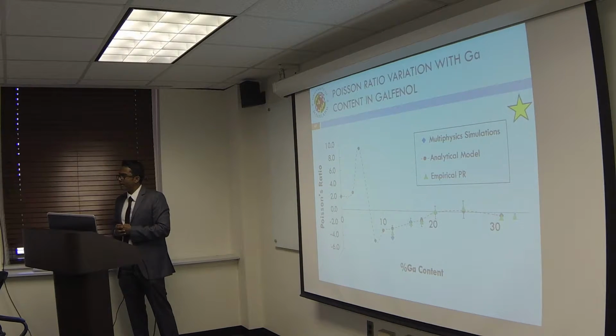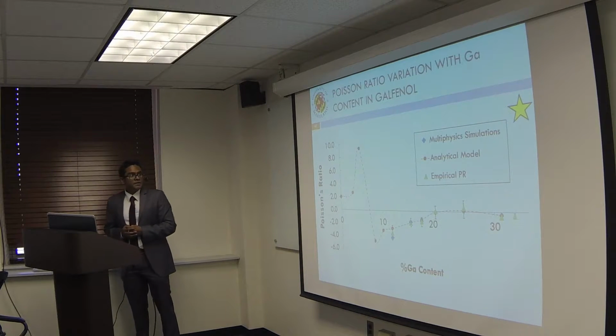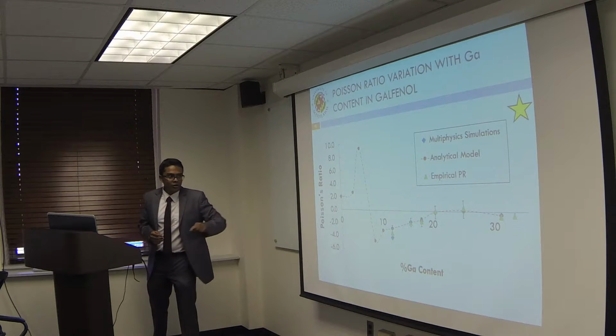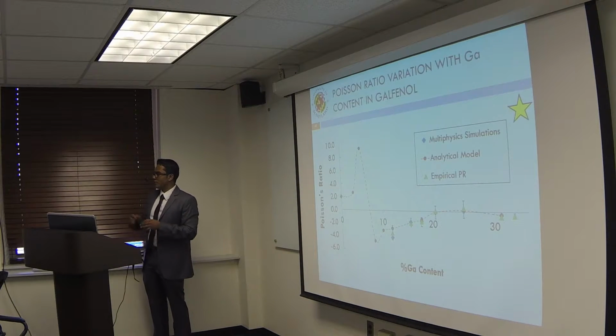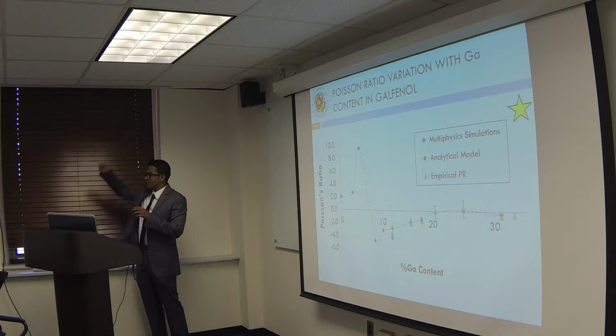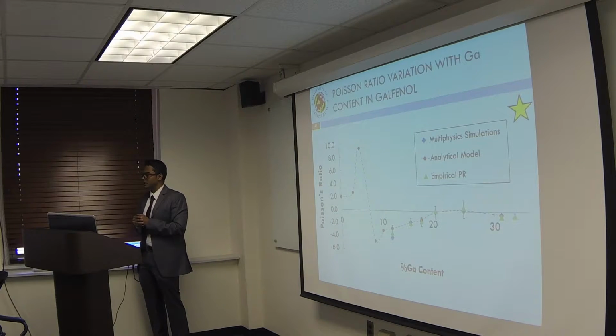So because of the atomic ordering? Yes. And the other reason is the values of strains are going to be really small because the more gallium I add, that's when I see the first peak in magnetostriction. So the values are going to be really small in terms of strain.